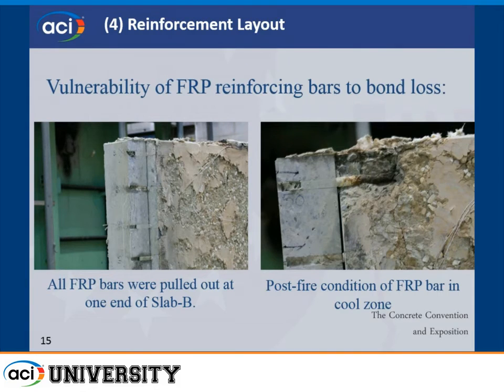And when we actually looked at what happened when the slabs did fail, it was due to the bond at the end. We could see some slip here of bars, and that's what precipitated the failure, but that was after the 3 hours of the fire exposure.